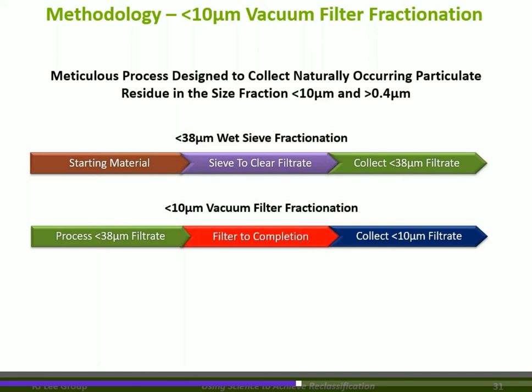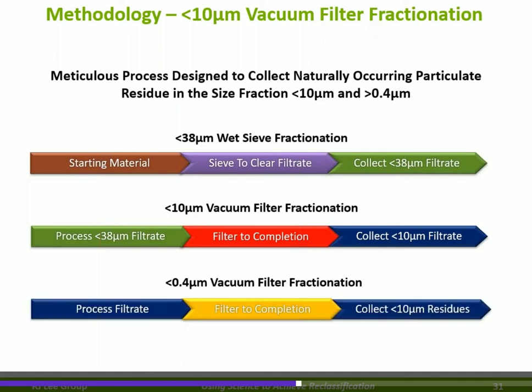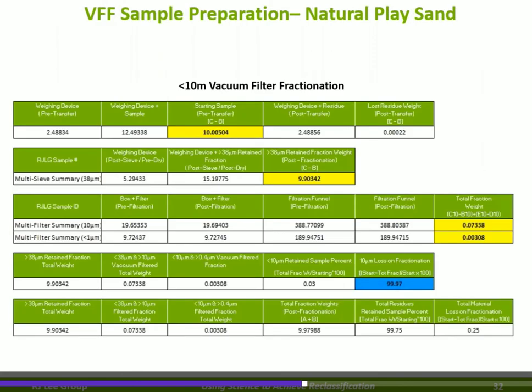Once we've collected the filtrate from the 38 micron, we're going to process that filtrate through a 10 micron vacuum filter, and we're going to get rid of everything above 10 microns. We're going to put a backstop on it at 0.4. We let everything below 0.4 go because we don't care about it, and everything above 10 go because we don't care about it. We capture the residue that occurs between 0.4 and 10. That is the respirable fraction under GHS and Prop 65.